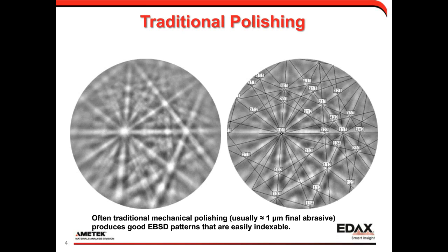This slide shows an EBSD pattern for what I've called traditional polishing, which is generally mechanical polishing down to something around a 1 micron final abrasive. And in most materials, this will often produce good EBSD patterns that are very indexable. We see diffraction bands there. We can detect them with a Hough transform.